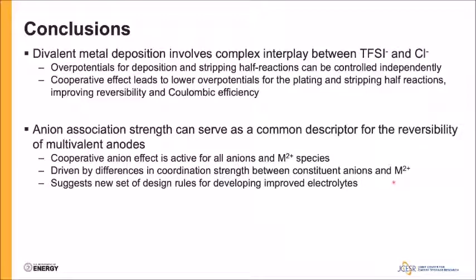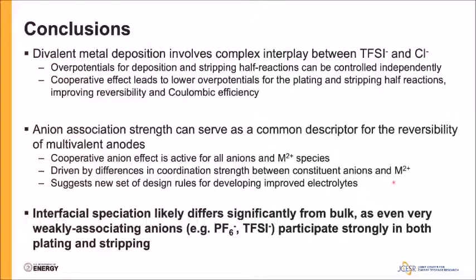And again, as I mentioned, this suggests a new set of design rules that we can use to develop new electrolytes. And the one comment that I'll leave with is that what these results seem to suggest is that interfacial speciation likely differs significantly from what we see in bulk measurements of electrolyte composition, as even these very weakly associating anions like TFSI and PF6 in particular appear to participate very strongly in both the plating and stripping reactions. And so even though these species appear to form solvent-separated ion pairs in the bulk electrolyte, clearly they begin to associate more tightly with the cation as they approach the electrified interface. So we have to think more about that as we move forward in our understanding of these electrolyte systems.